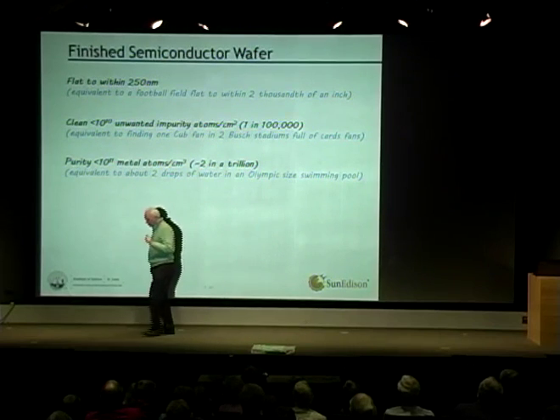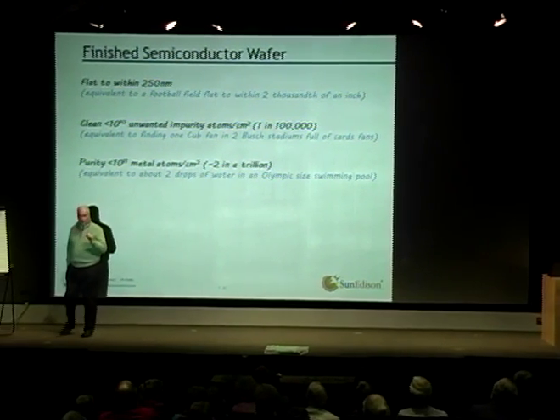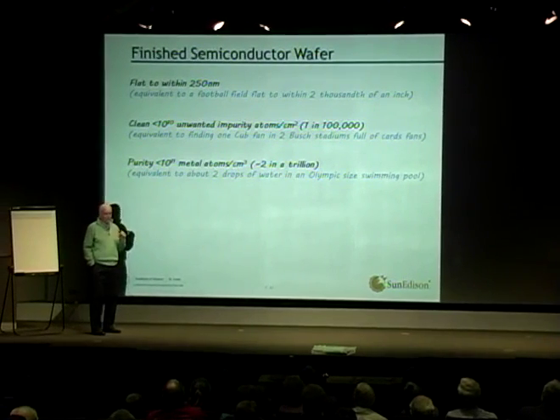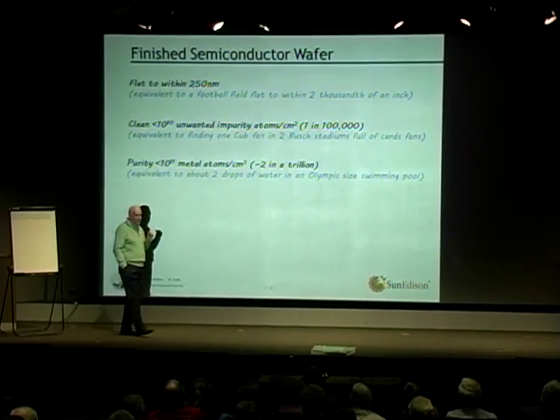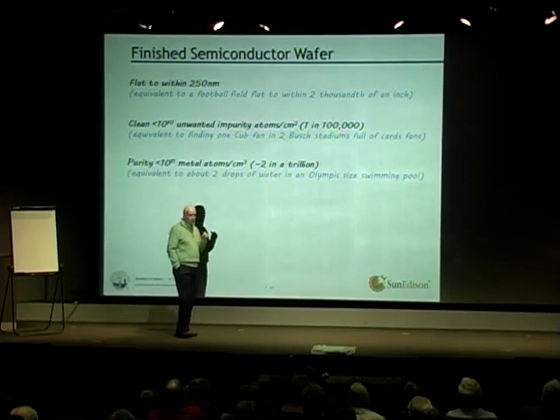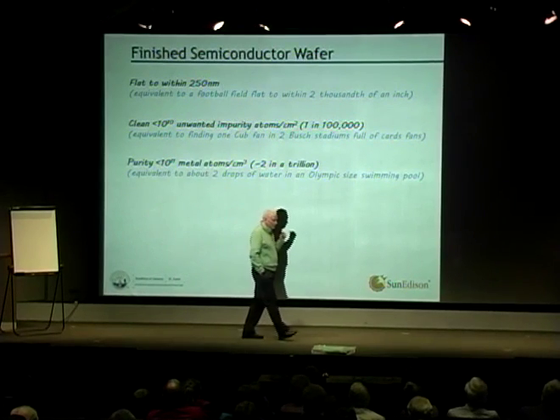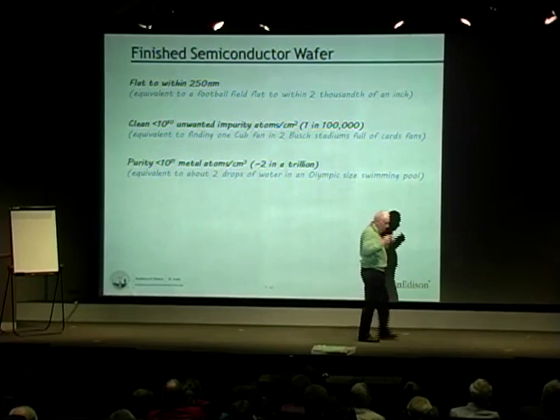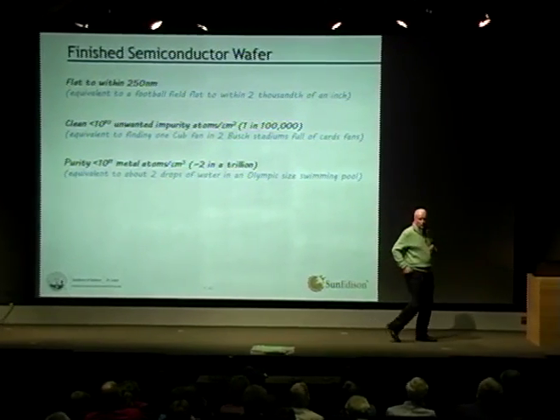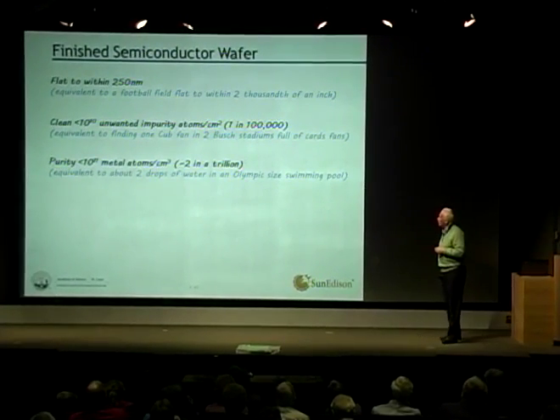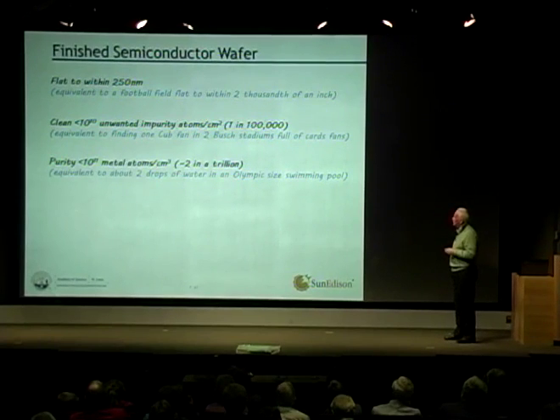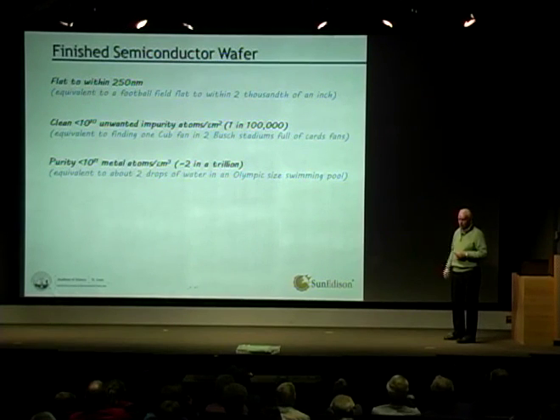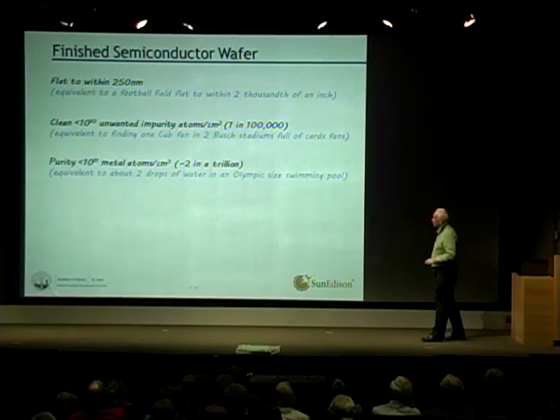So there are some very interesting statistics. One I really like is that the number of atoms in a teaspoonful of water is equivalent to the number of teaspoonfuls of water in all the oceans of the world. You start to get a sense of the sizes that we're talking about. So here, we're counting the atoms. We get down to about 2 parts per trillion. That's equivalent to taking one of those little eyedroppers and putting 2 drops into an Olympic swimming pool. That's how pure the bulk silicon that we produce is.